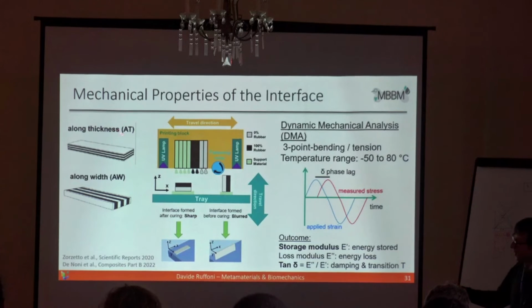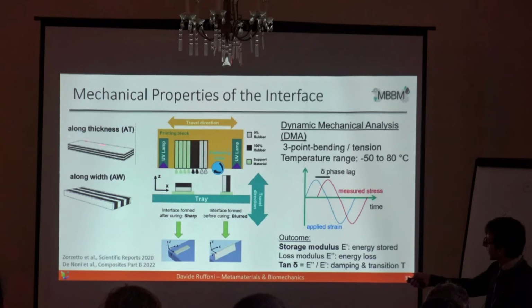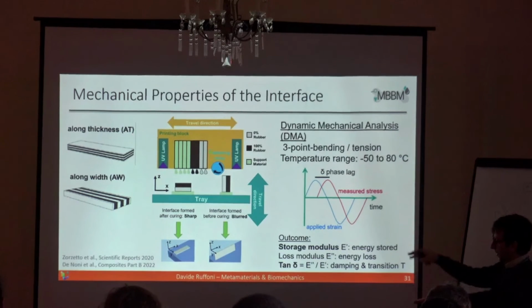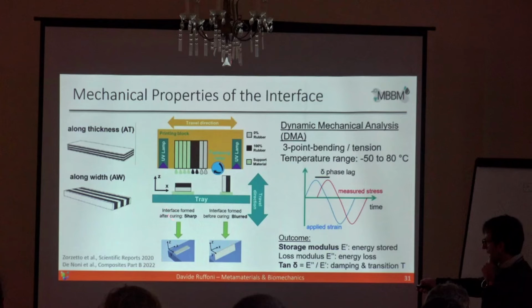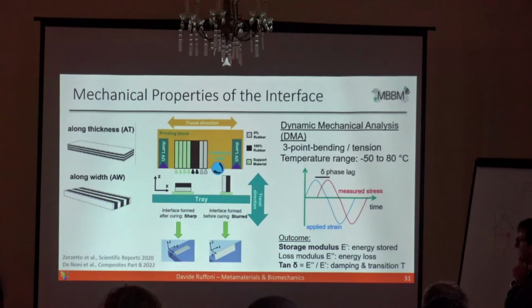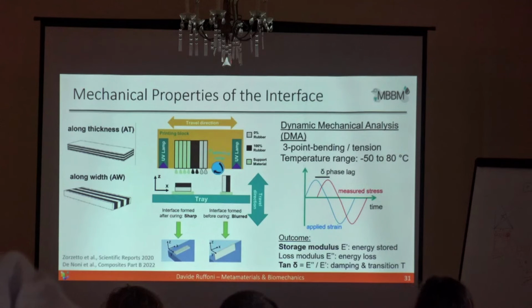So for that, we did a very simple design where we stacked different layers on top of each other, or parallel to each other, as in this configuration, and we printed this plate-like system to have the interfaces between stiff and soft component sharp, so formed after curing, 20 micrometer, or blurred, formed during curing, and so 150 micrometer. And then we investigated the mechanical behavior of this very simple system with the DMA. So we explored the mechanical properties by scanning the temperatures from minus 50 to 80 degrees to get the transition temperatures of the two components. And we focused a little bit on storage modulus and tan delta to see what was happening.